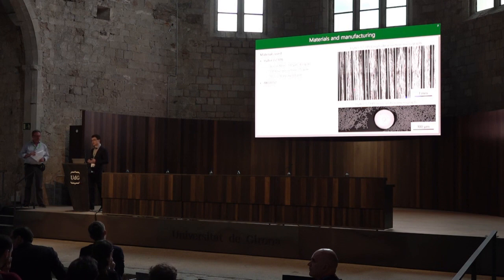So it depends on the carbon fiber, but yes, that's a good question because boron fiber does not behave as well in tension as it does in compression. So if you have a very good carbon fiber, then hybridization with boron would degrade the tensile strength a little bit, at least. If you have a not so good carbon fiber, then it may not.